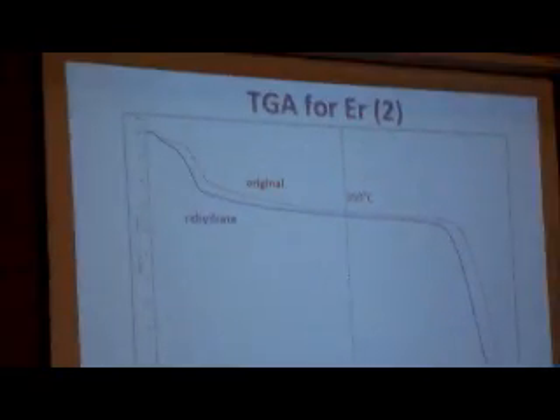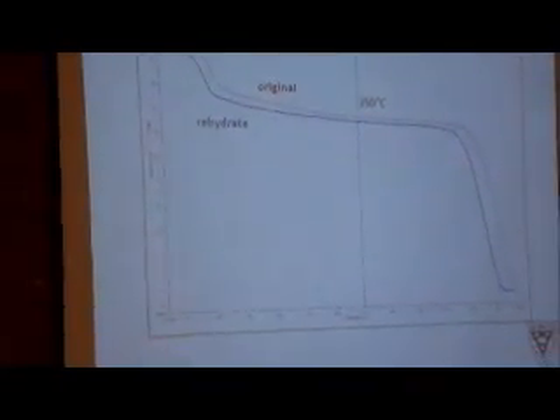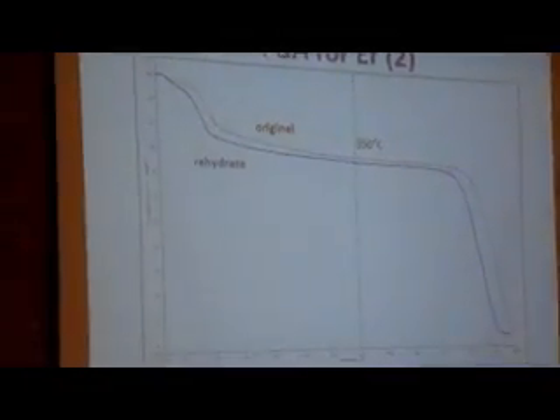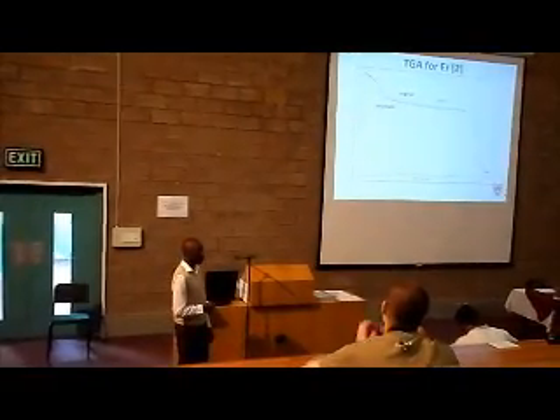Now, just looking at the TGA data on the thermograph, you can see from the original spectrum, which is heated all the way up until 650 degrees, we have specific stages where lots of water is lost. According to literature, to afford the completely anhydrous form of the MOF, you have to heat the MOF to 350 degrees. Now, you can see that the rehydrated MOF pretty much emulates the thermograph of the original structure, which is pretty exciting as well. And this is why I say that the erbium MOF afforded me the best product, as this was the best thermograph which was seen.